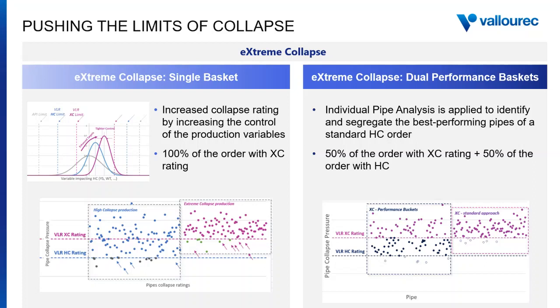Okay, so there are two things. Yes, our high collapse and extreme collapse offer have an inspection or quality control process that is tighter than the standard API product, right? So at the end of the day, that is one of the strengths of our high collapse methodology, and it's one of the steps that will allow us to offer these higher performances. So just to put it very simple, what we do for our high collapse and extreme collapse offer is that we check pipe per pipe in order to guarantee that the production targets that were set are achieved. So at the end of the day, you know that every single pipe that you receive from a high collapse or extreme collapse lot or order will achieve the collapse rating that we have guaranteed to you.